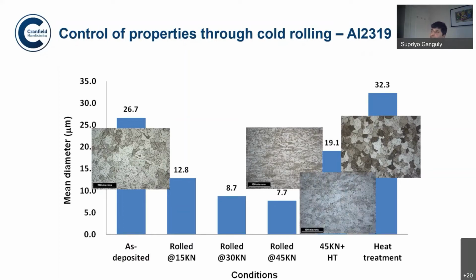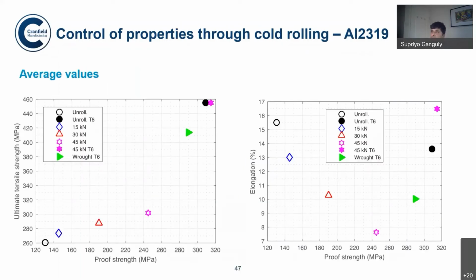With only rolling, you can have pancake-shaped grains, but after heat treatment it forms an equiaxed structure. This is a very interesting observation with aluminium, because these are all age hardening alloys. So basically, whether it is from a mill or through this process, you need to do a heat treatment, and it can be done as a T6 heat treatment, which basically means artificial